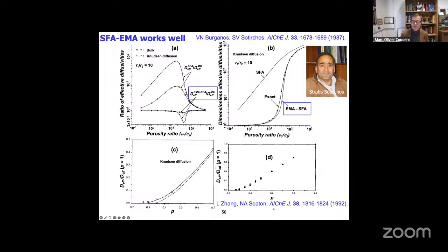Zhang and Seaton went even a level further and used continuum theory, comparing it for realistic models with a pore network model. And so if you have good connectivity and even chemical reactions, they find, again, that you have pretty good agreement. But what it highlights to me is that you need good models at the pore level. Yeah, so you need to include morphology, because what none of these models does is include morphology. They assume typically smooth, long cylindrical pores or spheres in other situations.